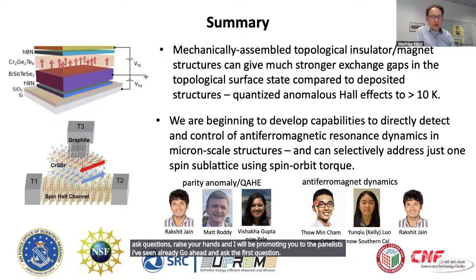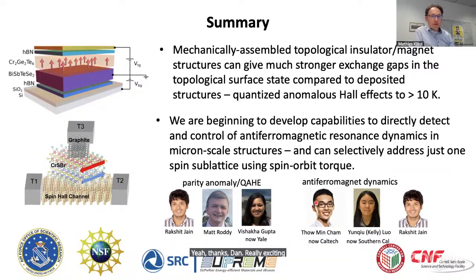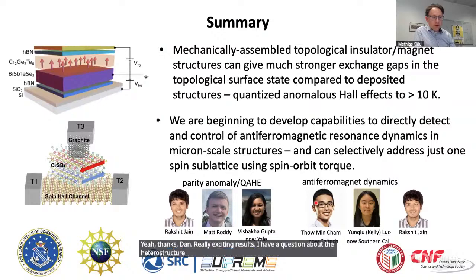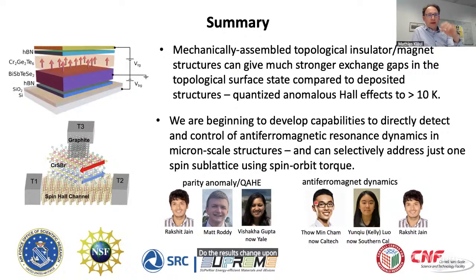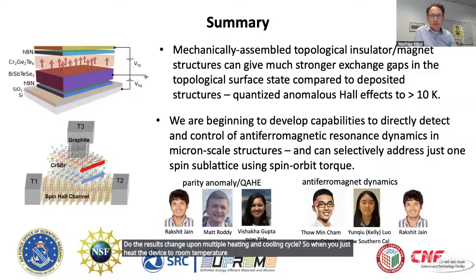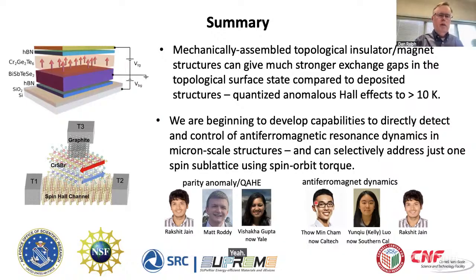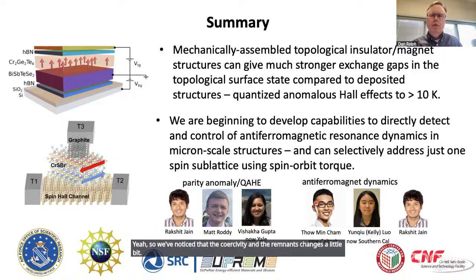Yeah, thanks, Dan. Really exciting results. I have a question about the heterostructure where you showed this topological insulator in contact with a ferromagnet. Now, do the results change upon multiple heating and cooling cycles? So when you just heat the device to room temperature and cool it back down, does it change? Because we've seen that the van der Waals gap can change as you heat and cool due to different thermal expansion coefficients.